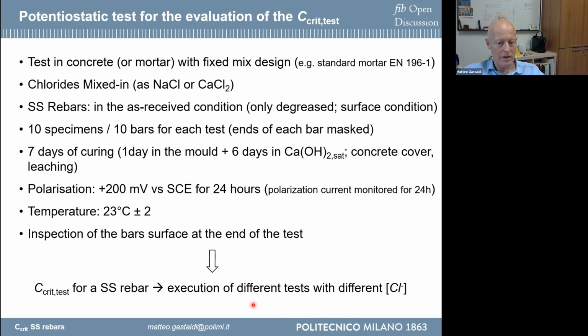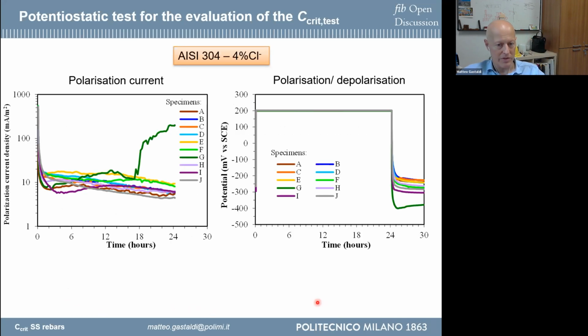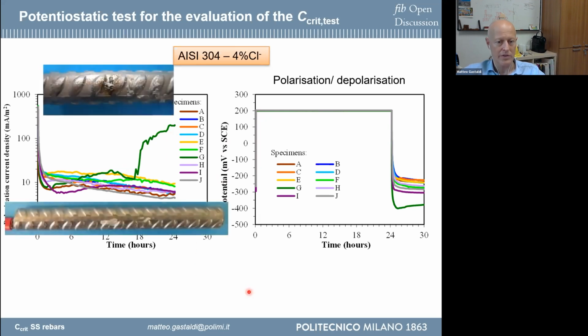You have to consider that if you want to have the critical chloride threshold, you have to make the test for different amounts of chloride. This is an example of the result of one test. You can observe that in one sample you have an increase of the current, and this shows that during the polarization at 200 millivolts, you have corrosion initiation after the test. You can observe the initiation of corrosion in the sample.